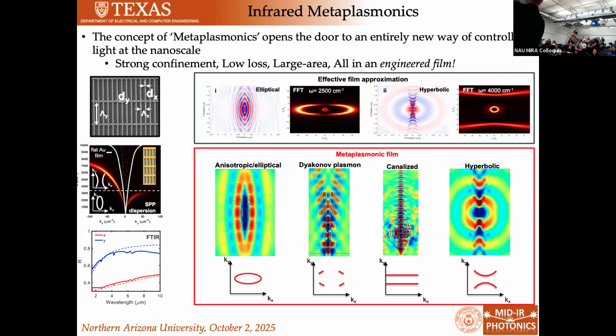If you take the Fourier transform of this mode profile, what you see is an isofrequency curve in k space. So this is all the same frequency, right? And you can see that for that frequency, you have a larger kx than you do ky. So this is essentially an anisotropic medium, but you can actually look at this film in regimes where you cannot propagate in X, but you have a dispersion in Y, and that gives you something that looks like this. This is the mode that's generated by a dipole sitting right above one of these films in a region where the film behaves like a hyperbolic medium.